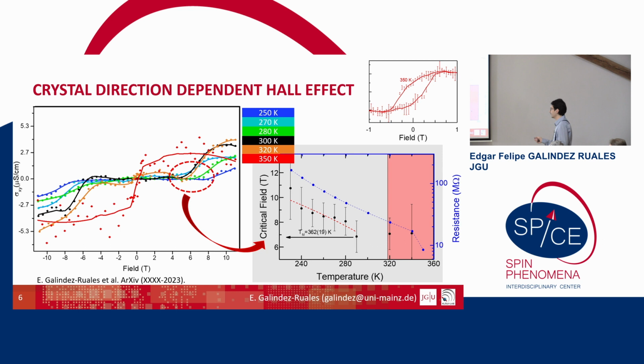Just to note, by the end of this slide, I want to tell you about how we were measuring the longitudinal resistivity. The longitudinal resistivity of the sample was varying a lot with the temperature, as we expected, and I showed you in the first slide, when you dope it, you have a jump in the behavior. This jump is also consistent with the Morin transition that is predicted by the Landau theory. That was just a curiosity.